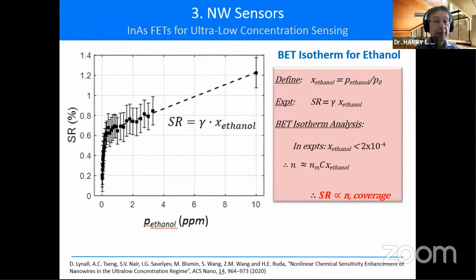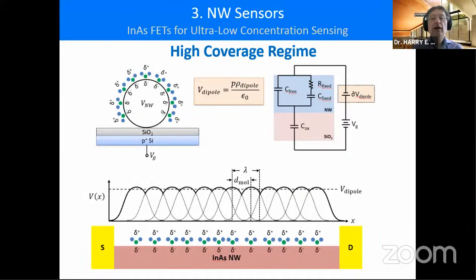So when you put that back into the BET isotherm, you see that that isotherm becomes a very simple equation, which means that the number of adsorbed molecules is basically going linearly with the exposure. And indeed, that linear fit works very nicely for relatively large concentrations or exposures, as shown on the scale of this ppm scale figure. It fits very nicely to that data. Okay, and what's going on? How can we explain this behavior?